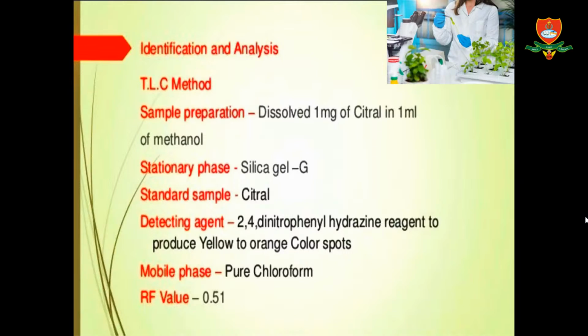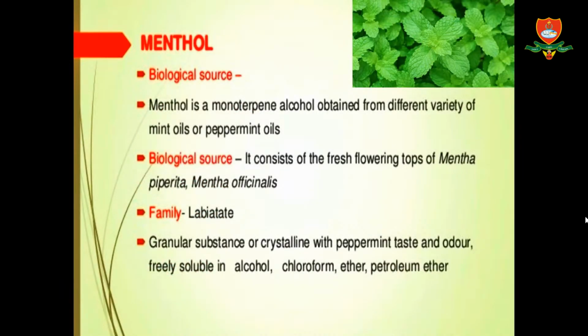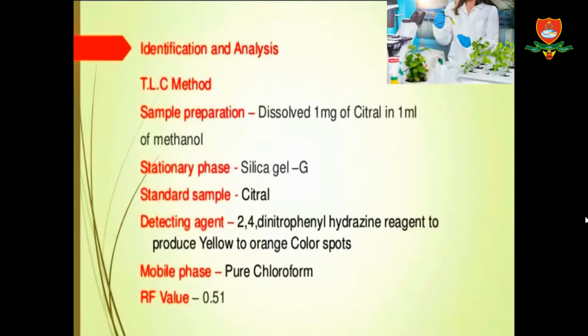TLC. Then we carried out the thin layer chromatography method. For the sample preparation, 1 mg of citral is dissolved in 1 ml of methanol. The stationary phase we took is the same, silica gel G, and the standard sample is citral. We used the mobile phase as pure chloroform, and the detecting agent as 2,4-dinitrophenylhydrazine reagent to produce yellow color spots, and the Rf value thus obtained is 0.51.